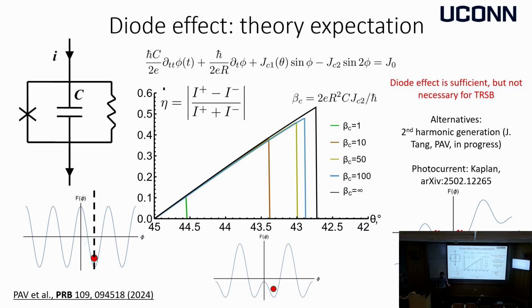So indeed at 45 degrees there's a reason that the diode effect can vanish. But what we also demonstrated is that if you see the diode effect, that means you do have time reversal breaking, but actually it is possible that all of these curves are in the time reversal broken phase, but some of these curves show no diode effect for a long range of twist angles, which means the diode effect is a sufficient, but not necessary criterion for time reversal symmetry breaking. And one of the directions I'm working on is different probes of time reversal breaking in these systems that will allow us to characterize this phase better. That includes second harmonic generation, which turns out to be necessary and sufficient, and photocurrent probes.